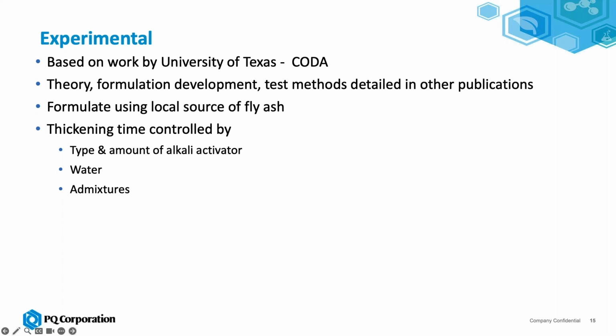Now the downside with too much water is it decreases the compressive strength. So there's a bit of play off between having desired viscosity, thickening times, and maintaining compressive strength. We've looked at admixtures. A couple products showed some potential retarding, but we found that we could get the desired set times just by choosing the correct activator and having the desired water level. Next slide.